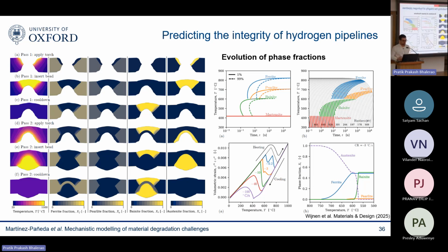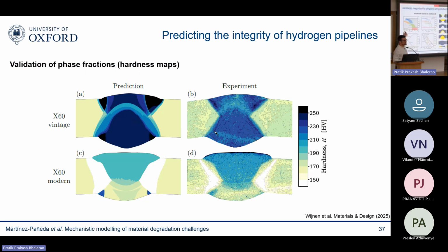And one thing that you can do is relate the phase fraction with the hardness. Then you can create these hardness maps that you can compare with experiments. You can see here, the agreement, in my opinion, is pretty good. We were basically told this is the way the welding was done, predict the phase fraction evolution, and then from there determine a hardness map, and then we'll show you the hardness map that we did in the lab. They're not identical, but this is the same scale, and they show very similar features.